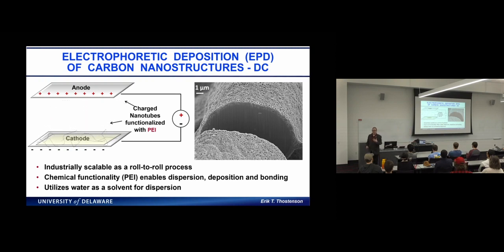And we can use both direct current and alternating current. But on the right-hand side, what you see is a cross-section of a fiber. When we deposit, it's not really just like the tubes are raining down onto the fibers or the fabric, but it actually coats it and gives us a very, very uniform fiber-level coating. It's almost like a sponge. That's what you see in this texture up in here.